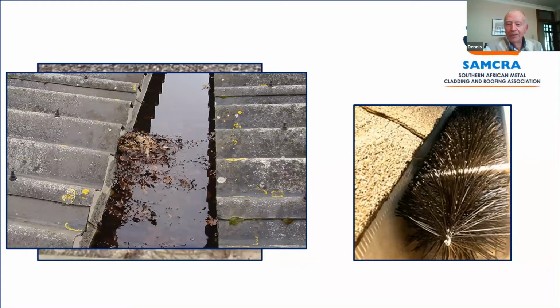Yeah, and if you consider the dust that accumulates on a roof inland during the winter months, and then we get a heavy dew point, you've got a fair concentration of mud. We've had experience where the hole, the outlet into the downpipe, if it's not via a cone, so you just have a straightforward hole down into the downpipe, actually blocks up with dust and cements across, and you actually get plants growing in it. So keep the stuff out as much as you can, if you can.